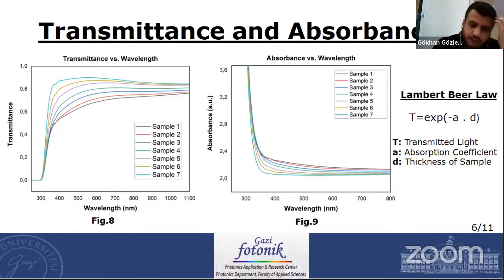In figure 8, it's shown that transmittance of the titanium dioxide films reduces as the thickness increases from 5 nanometers to 35 nanometers. Reduction in transmittance satisfies the Lambert-Beer law. In this law, T is equal to exponential minus A times D, where T is transmitted light, D is thickness of the sample, and A is absorption coefficient. With the increase of film thickness, the transmittance decreases slightly because more atoms are present in thicker films, so more states will be available for the photons to be absorbed. The absorption leads to transition of electrons from valence band to conduction band.